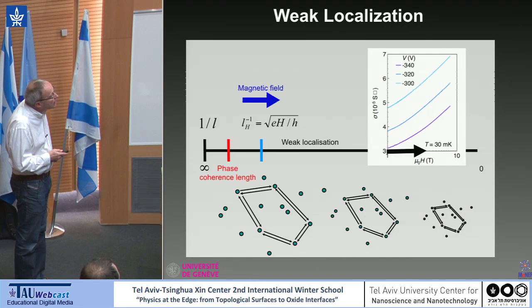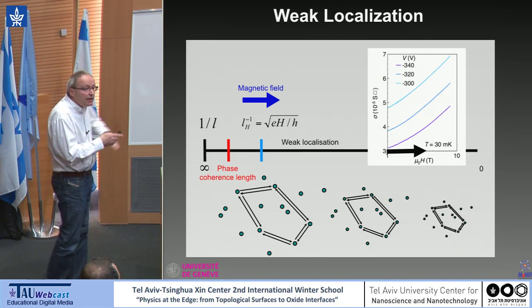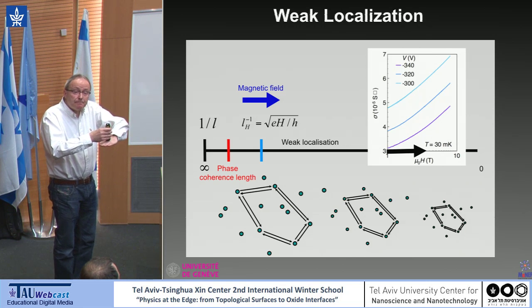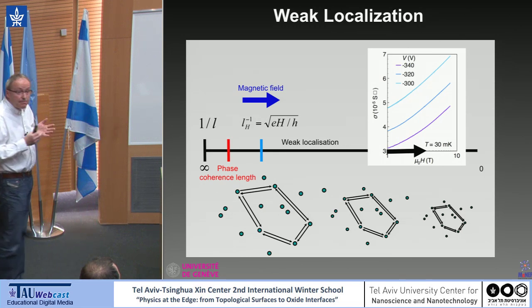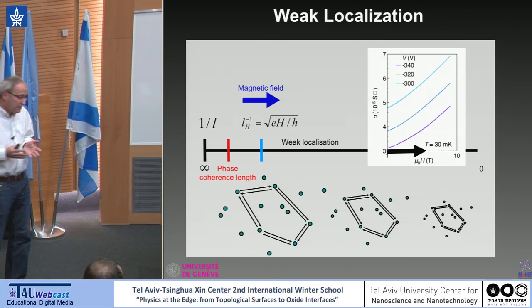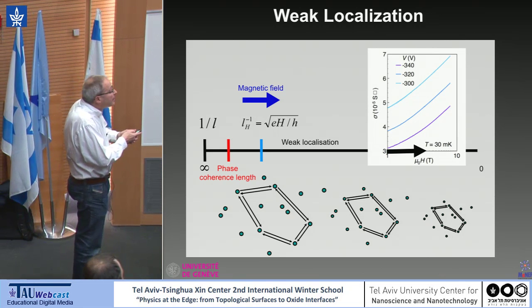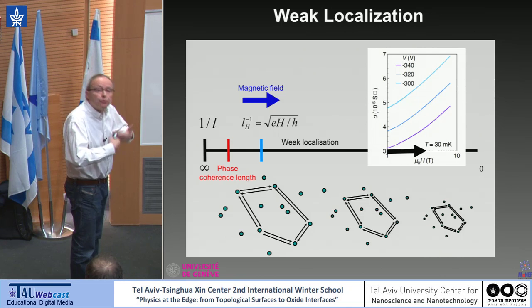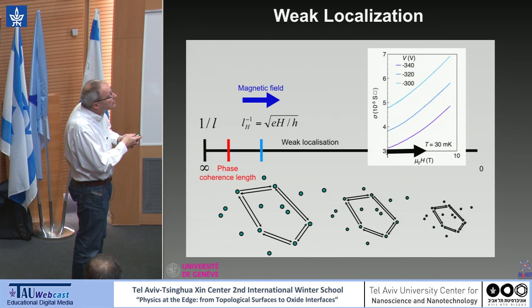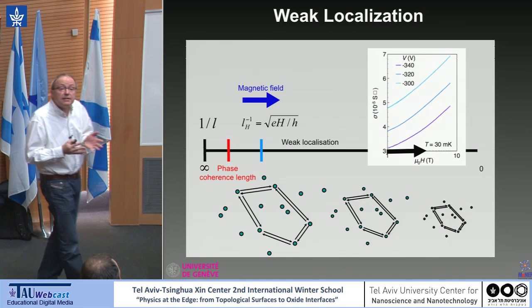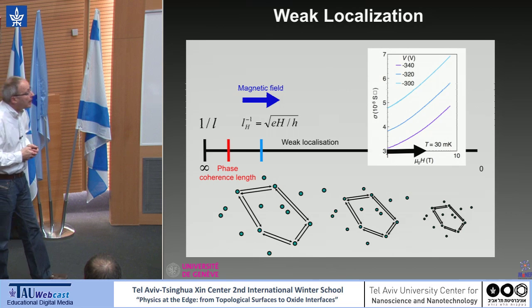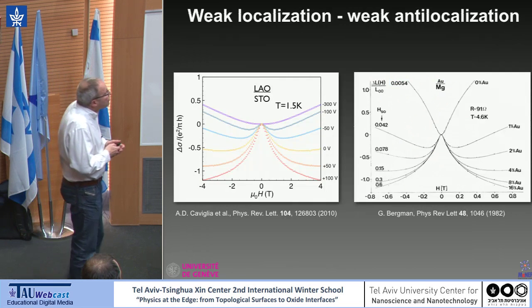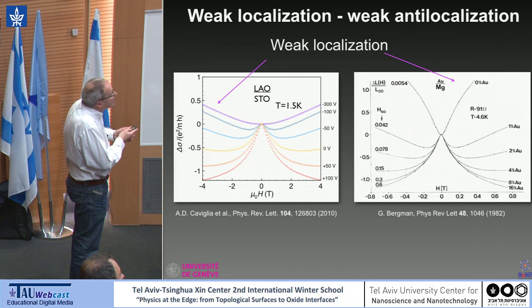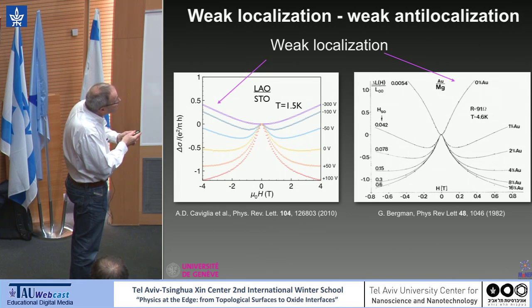So this weak localization, when you apply a magnetic field which is perpendicular to the plane, this magnetic field is breaking time reversal symmetry, and so you dephase the electron waves, and so you restore conductivity, and this is why the conductivity is increasing. The characteristic scale for this is e squared over pi h. Now, what you see here is that when we increase the carrier density, the behavior is changing. First, you see a small dip, and then it's going up.